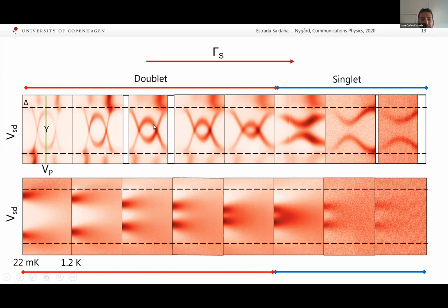So in each of these loops, we're taking line cuts, and we're plotting this versus temperature. So this is how the YSR peaks evolve at the electron-hole symmetric point versus temperature. And we see that they split with temperature. And when we reach the loop that is the smallest, the YSR peaks converge towards zero energy, zero bias, with temperature. And when we cross to the singlet side, they converge even faster towards zero bias, even though they are at the same initial position. So there is a difference between being a doublet, being a singlet, and the position inside of the peak.